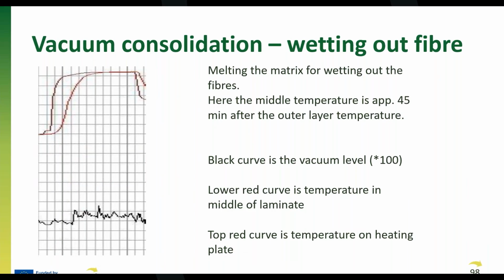Here you actually have the wetting out of the fibers. The fibers, you can see, need to be wetted out, so you have to go above the melting point of the polymer because you have to move it. And here it goes up, and again you can see, due to the thick laminate we have here, that we are running like 45 minutes after the outer layer temperature. So you have to take a time, according to the equation as shown in the beginning, before you have moved your polymer throughout all the filaments. And the vacuum level, you have to make sure that you are keeping nice and flat at the bottom here. Next one, please.